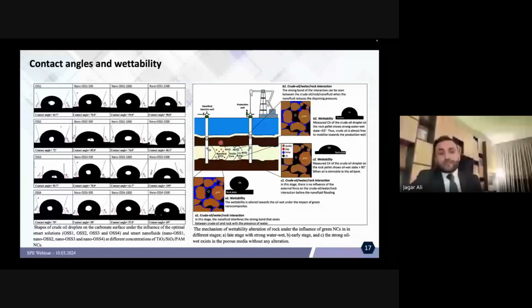So usually we reported this mechanism as the wettability alteration under the influence of the nanofluid. As can be seen, when we have an oil bank, it is almost oil wet, and oil is attached to the rock as a residual oil, as a trapped oil, so it cannot be moved. Then when nanofluid tries to penetrate this zone, and we have a transition zone between the nanofluid and oil bank, the contact angle will be changed and reduced till it completely becomes a nanofluid bank, and then what will happen? Contact angle will be reduced highly to strongly water wet, and then hydrocarbon will be free to be moved.